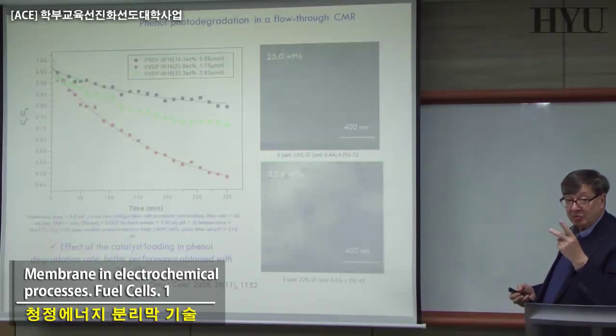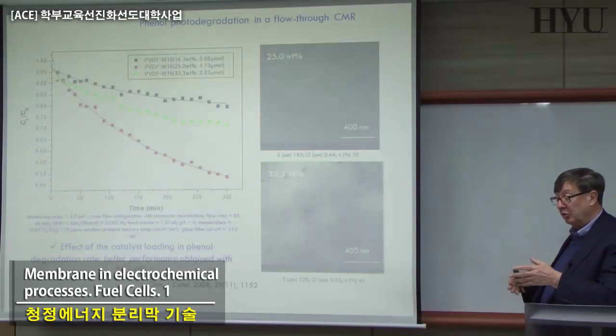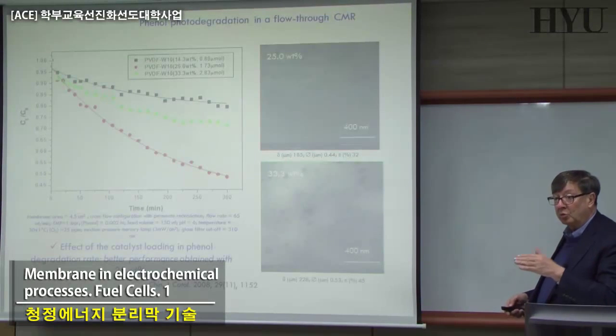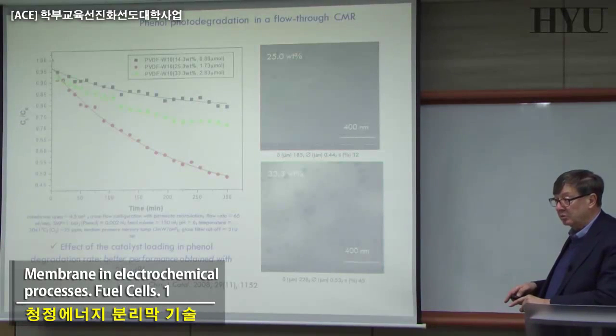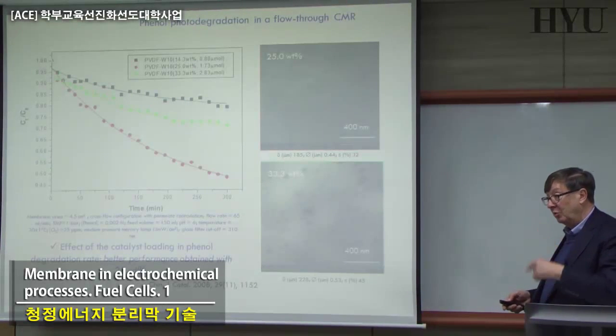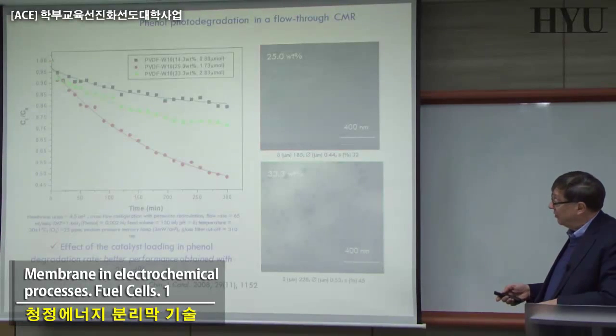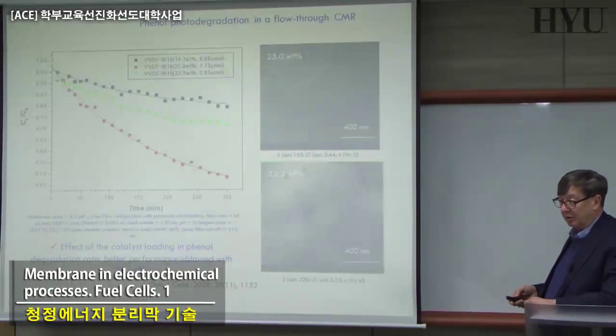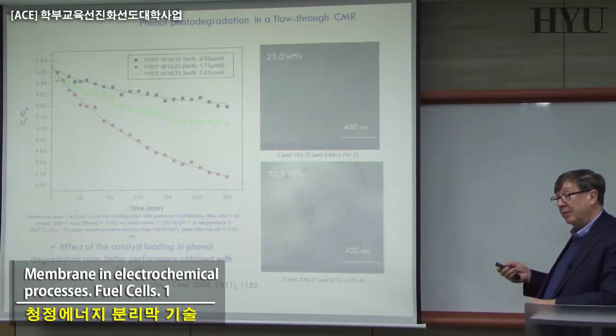One can be leakage. That means during the operation, when you put the system in operation, slowly you can lose some of the catalyst in the solution. And you don't want to do this because we want to recover and reuse as much as possible. So you have to optimize the percent of the catalyst that you are adding to the polymeric system. And you are also changing, by the way, the mechanical properties, which can be in some cases positive, in some cases negative.